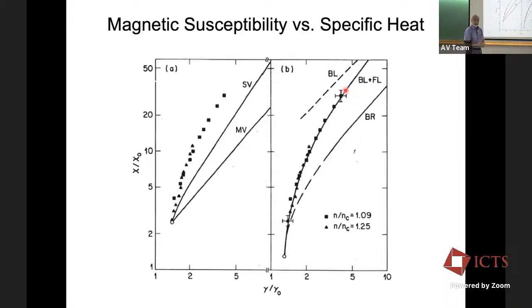And the mass enhancement, actually, we don't adjust. We take it from the Japanese measurements on phosphorus doped silicon in the range 1 to 2 NC from the 1960s and 70s. And that number is something like 2, 2.5 or something like that. And we just took it, whatever it was. And when you add the two, you find that the data exactly goes over the curve. There are no adjustable parameters because alpha has already been determined from the insulator. Beta of alpha is known. So we know exactly that curve. There is no adjustable parameter left.